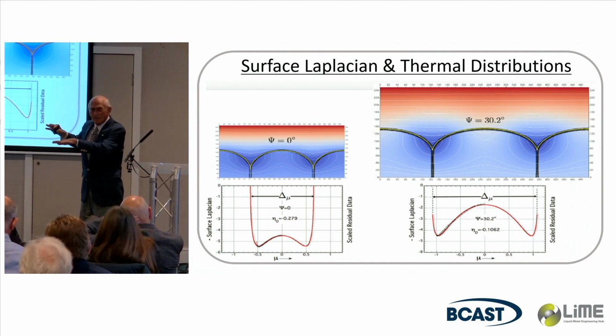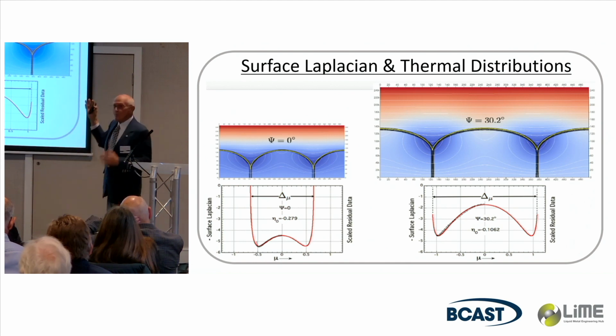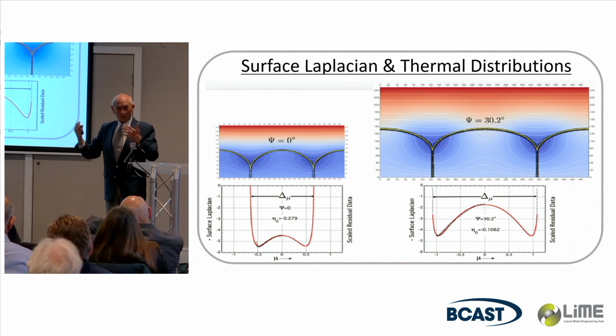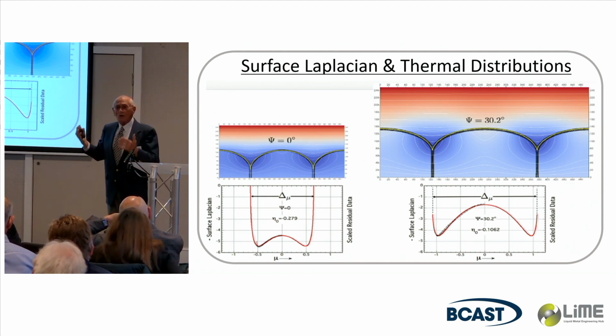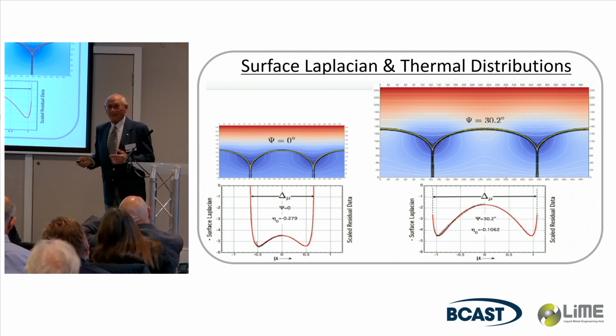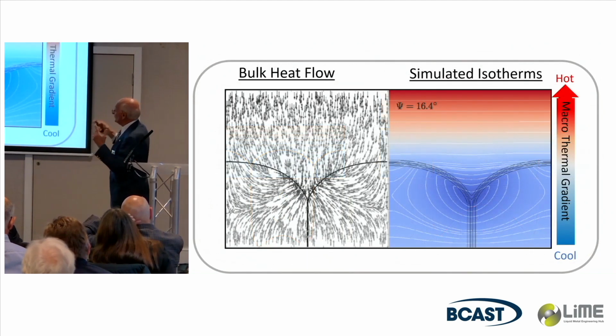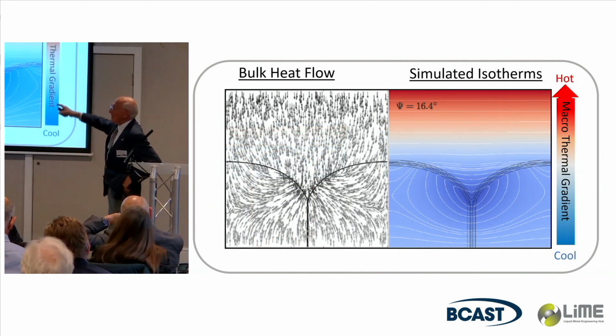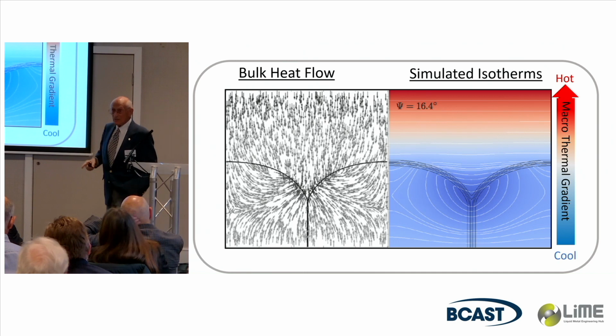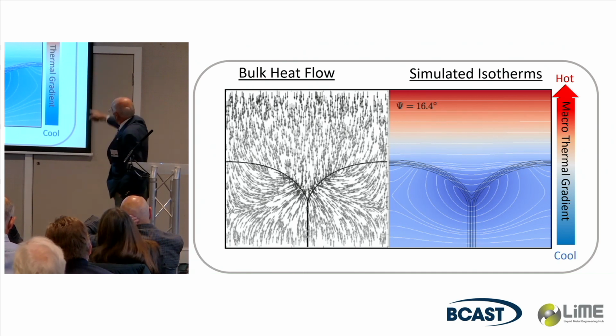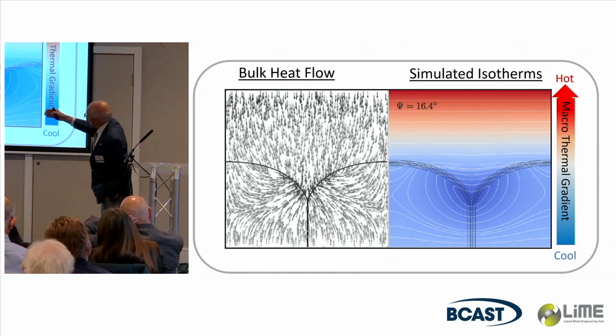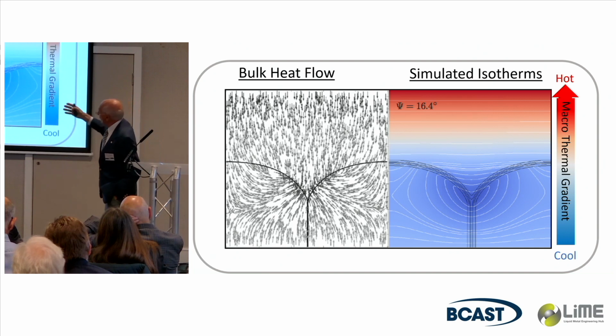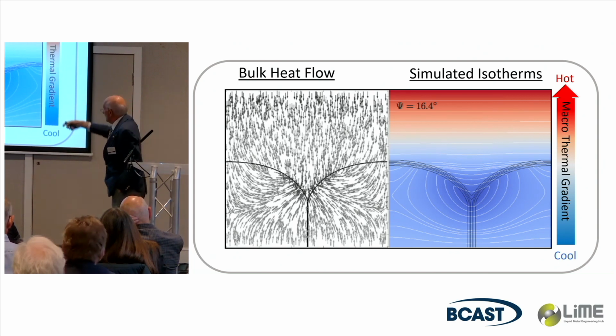This is a stationary interface. And what these results are telling us is there is a mechanism of thermal transport, I think it's a form of thermal diffusion, that goes on in castings that we're not particularly aware of. And just to check it, look at the vector map of the heat flowing near these boundaries. We have simply a macro gradient, which should give us perfectly straight vectors. You can see that these thermodiffusion effects actually suck the heat in near these boundaries.